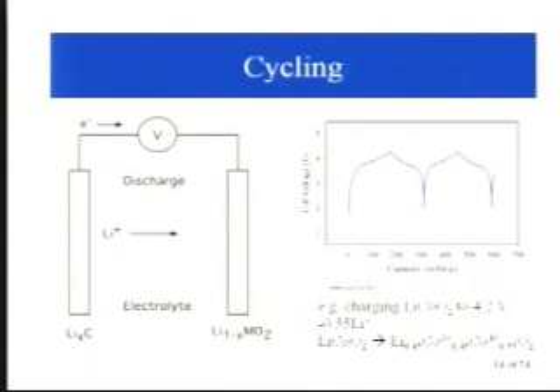So just to correlate this with a general cycle profile, if we start with the battery just assembled, a lithium-ion battery, as we charge it up, we're increasing the voltage, and the plateau where the redox potential is, that's where the lithium transfer takes place. You extract the lithium out of the material, and about 4.2 volts corresponds to about this much lithium taken out in the case of lithium cobalt oxide, which is a good model compound to use to explain this. And then the reverse is true, of course, on discharge. And so it's all about just trying to get materials that have the highest specific capacity.